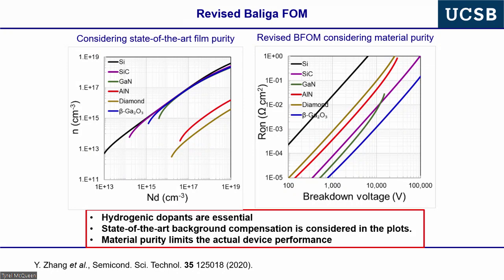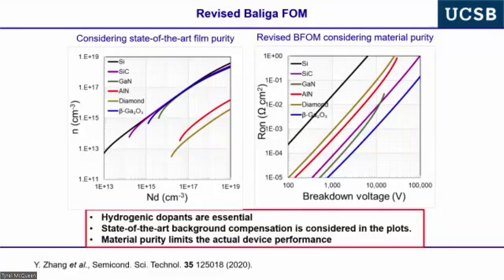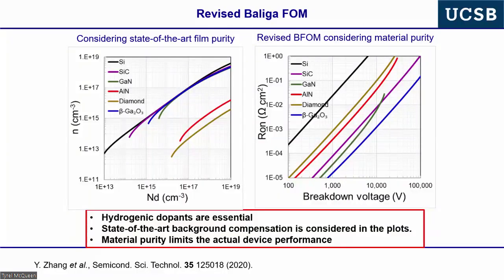Okay, so now I'll ask you a quiz. What's the atom density in any dense inorganic material? Any dense inorganic material. How many atoms per cubic centimeter? If that was silicon or GaN or silicon carbide, it doesn't matter. It's always within a factor of 2 because bond lengths are always about the same, right? So if you do the math very quickly, you're going to find in 1 cubic centimeter of material, there's about 0.1 Avogadro's number of atoms. It's always about 4 to 8, 4 to 10 times 10 to the 22 atoms per cubic centimeter, okay? But always, you'll get that number. Gallium oxide is, I think, 8 times 10 to the 22 atoms per cubic centimeter. GaN is very similar to it because atom spacings are all approximately the same, okay?